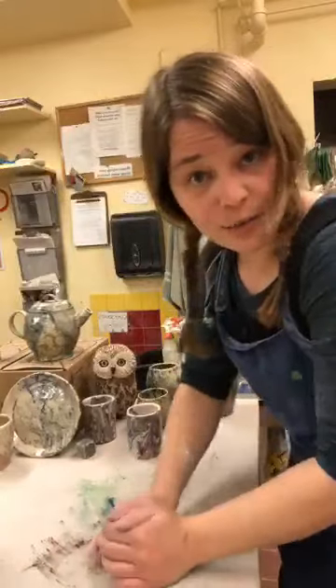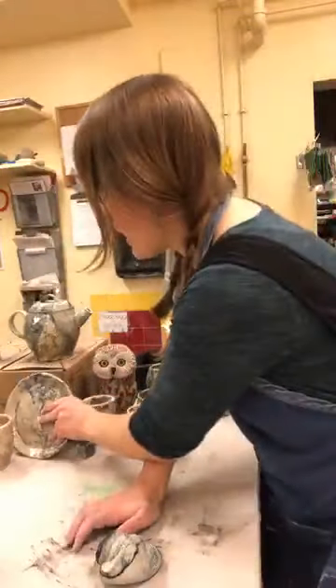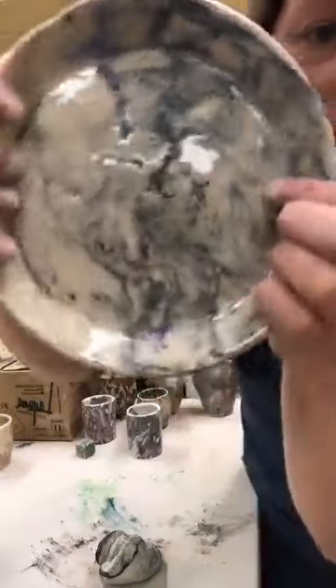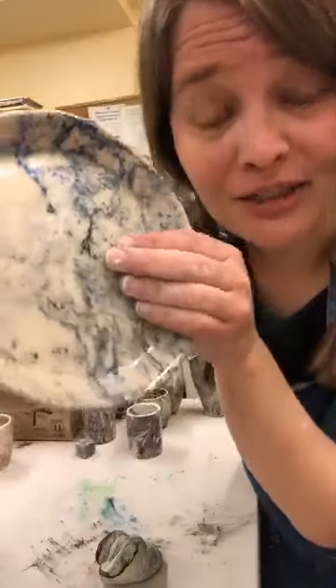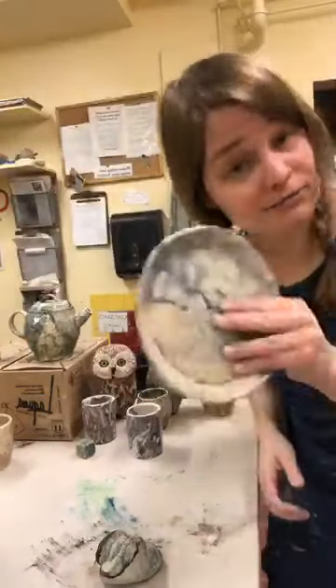If I start making the pinch pot before the stains are fully incorporated, I'll have seams burst open and the mason stains spill out. Here's a piece I kept because it wasn't sale-worthy — you can see where the clay has split and I have mason stains coming out. That's a fault we don't want.